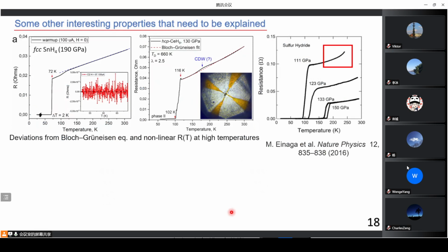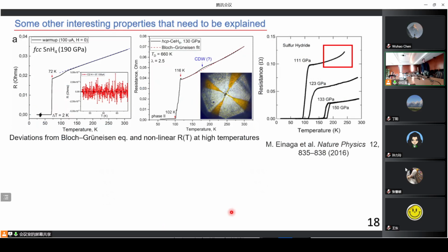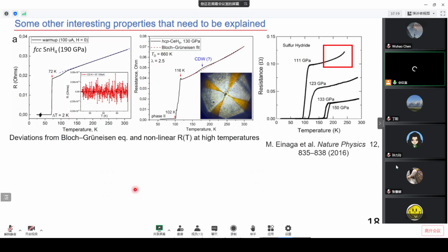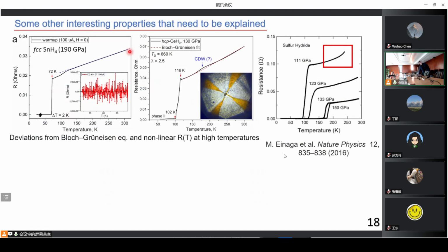There are some other interesting properties that need to be explained. It's, of course, the non-linear behavior of resistance, and sometimes it's very linear, which is also unusual. For SnH4 at 190 GPa, we observe these curves, and they are very well reproducible. We see it's completely linear between 150 and 300 kelvins, and after that suddenly changes and becomes non-linear.